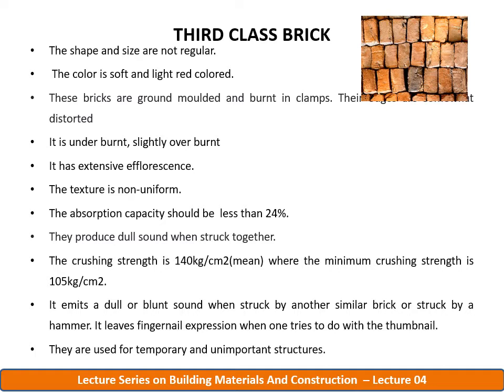The absorption capacity of these types of bricks should not exceed 24%. They should produce a dull sound when struck against each other. The crushing strength is 140 kg per centimeter square, where the minimum crushing strength is 105 kg per centimeter square, and it emits a dull or blunt sound when struck by another similar brick with a hammer.